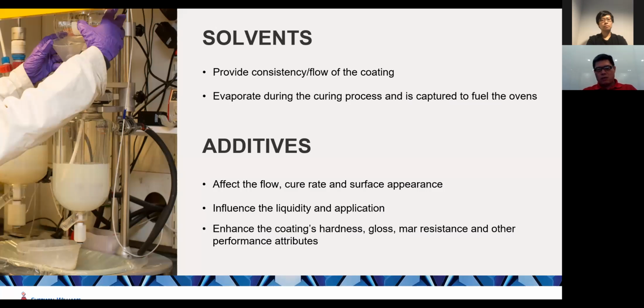And specific to the application, additives are used for processing pigment within the film for flow and smoothness, for regulating the rate of cure, and for enhancing the cure hardness, gloss, and mar resistance, and other performance attributes. So a lot of these terms you may not be familiar with, but if you look at the panel, I think Florence showed us the panel, the black color, okay? If you look at the panel, it's smoothed out and very evenly distributed. And that's the effect of these additives, okay? To make the flow a lot better, make the surface look so much smoother, okay?